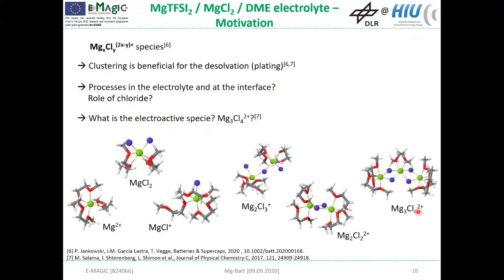So let's now have a look at a different kind of electrolyte which contains chloride. As you already heard, it is known that the magnesium cations form various different smaller and bigger clusters with chloride anions, and that although the chloride-containing electrolytes are corrosive, they are often used because this clustering with the chloride anions seems to be beneficial for the desolvation, and therefore it facilitates the cycling reaction.